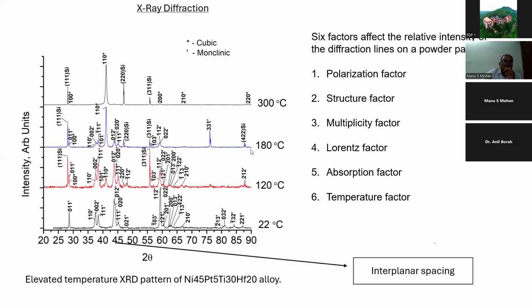Now, if you increase the temperature, what will happen? At close to 180 degrees Celsius, you still have peaks, but the moment you go to 300 degrees centigrade, many of the peaks disappear, because this is a shape memory material. Shape memory material means there is a transition from monoclinic to cubic phase at higher temperatures, so at higher temperatures you see the disappearance of the peaks.